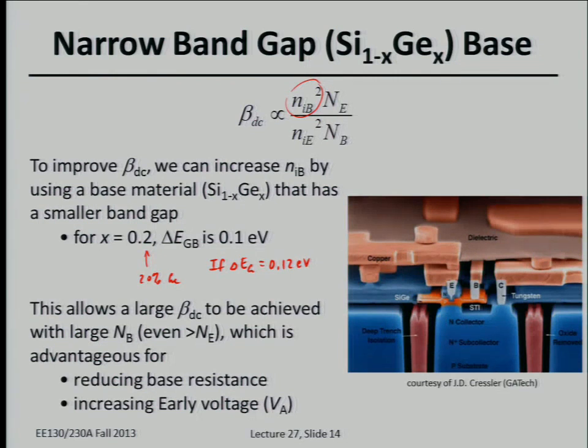What's nice about that is, if Ni squared can be increased by orders of magnitude, that allows us to increase Nb, the base doping concentration, and still have a beta that's pretty high. That's advantageous because then we can reduce the parasitic base resistance and also reduce the base width modulation effect. So that means we can increase the Early voltage, have flatter IV curves in the active mode, and that gives higher performance, higher gain for amplifier applications.